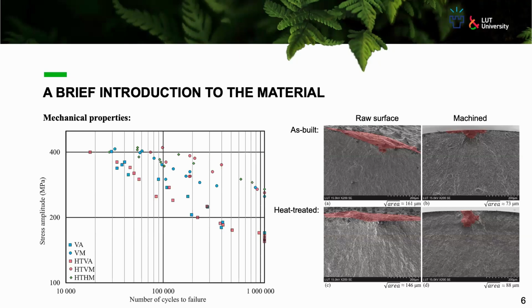The fact is that the high strength of these materials after heat treatment relies on the presence of these micro- and nanoscale precipitates. On the other hand, the material becomes more defect sensitive, and even in some cases, these precipitates that are supposed to contribute to the high strength of the material can act as failure sites for fatigue, especially in high cycle fatigue case studies.